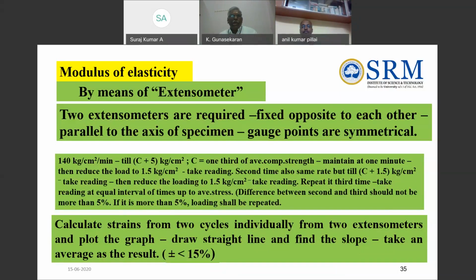Actually, if you want to get the real value of the modulus of elasticity, it has to be done like this. Knowing the average compressive strength of your concrete, you have to apply a load or stress up to the limit of C plus 5 in the first cycle. Then you go up to that level and release it to the point of 1.5.